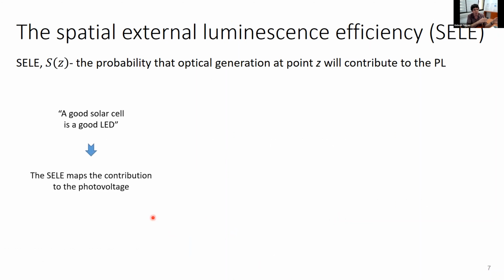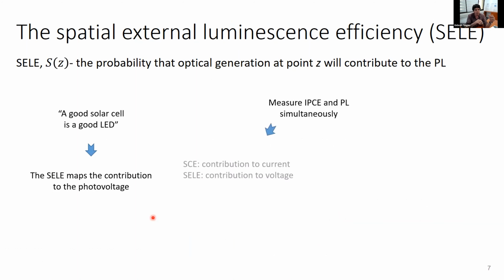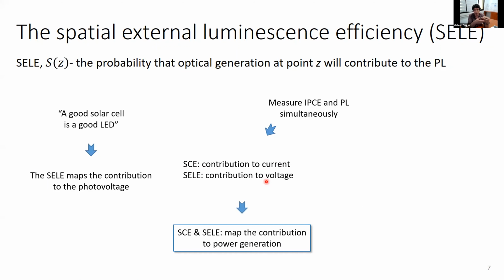So SELE can tell us about the contribution to photovoltage, but perhaps you can also measure both IPCE and photoluminescence and now get some added value here to make some synergy by looking at these two together. So first of all, the spatial collection efficiency tells us about the contribution to current, the SELE about the contribution to voltage. So if we look at both of them, we can actually map the contribution to power generation inside the device.